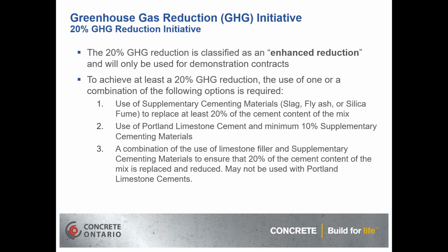The 20% greenhouse gas reduction is classified as the enhanced reduction, and that's going to be used for certain demonstration contracts. To achieve at least 20% greenhouse gas reduction, we have to use one or a combination of the following options. The use of supplementary cementing materials, slag, fly ash, or silica fume, to replace at least 20% of the cement content of the mix. Or we can use a Portland limestone cement and a minimum of 10% supplementary cementing materials. So if we used Portland limestone cement and 10% slag, that would give us our 20% reduction.